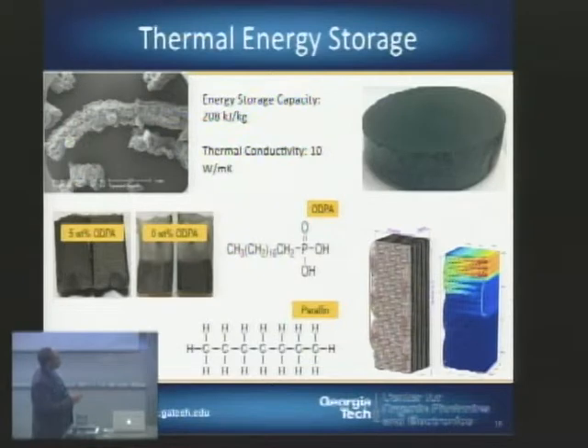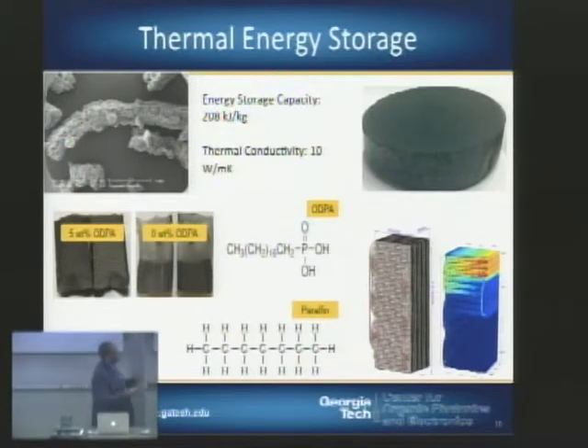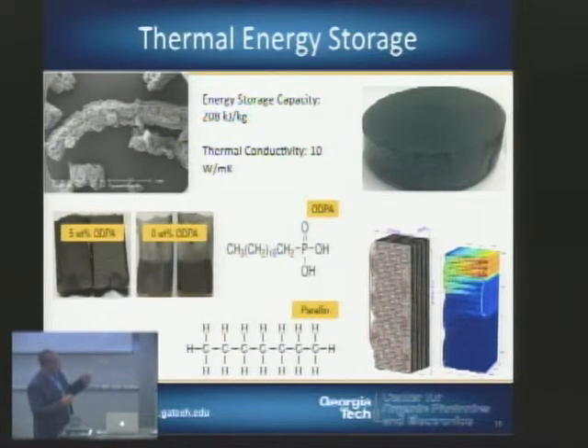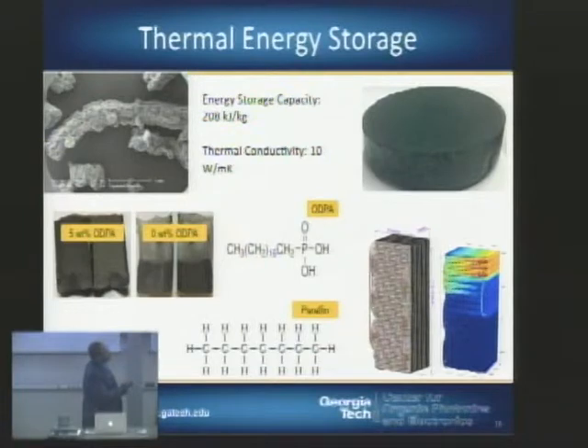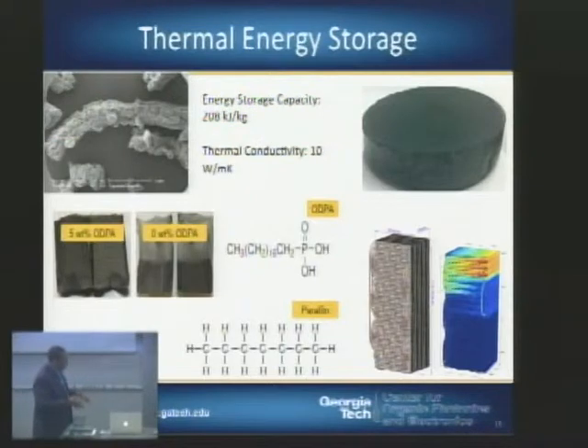We've also used some additional augmentation by mixing in graphite flakes, where we use octadecyl phosphonic acids that will stabilize these materials in suspension. So this is 5 weight % ODPA. What we do is hold the material in the liquid state, and if you don't have this ODPA inside, you'll see that the graphite will settle. And this hasn't settled over, I think, a 15-day period of being in the liquid state. These particles are about 15 microns in diameter, so fairly large, and so it's a fairly stable system. We're currently looking at the utilization of these in heat exchangers so that these will act as thermal batteries for storing waste heat energy for providing hot water to buildings.